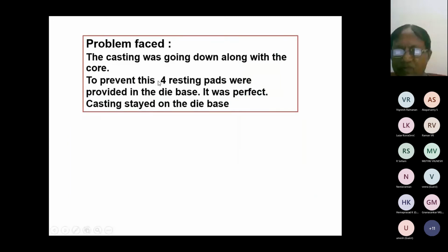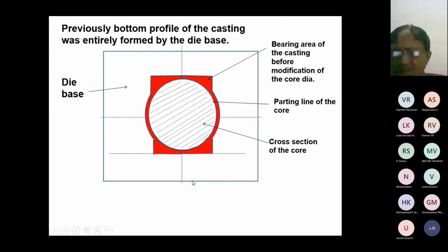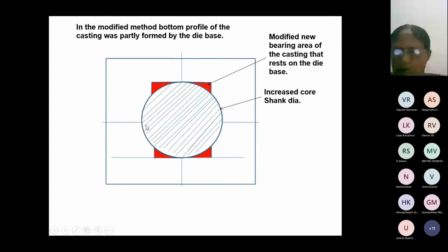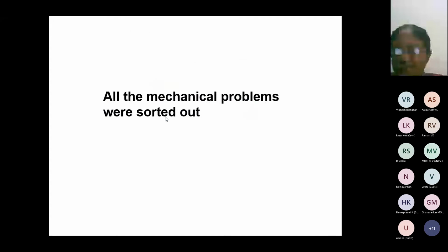So we have provided 4 resting pads on the die base like this. This is the casting bottom. This is the core shank, the cross-section area where the core moves down. We have provided 4 pads as a bearing area so that the casting is able to rest on this one and the core goes down. See, this is the core shank, which is about say 30 mm more. These portions are formed by the die base itself. So it is resting on this one and the core goes down. This was very much successful and we found the casting is working well. All the mechanical problems have been sorted out.